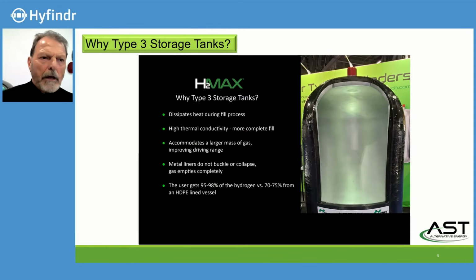Okay. And regarding the type 3, just also in comparison to the others in terms of operation and so on? Yeah, the type 3 has the big advantage. Aluminum is a very highly conductive material and therefore has a lot of dissipation of heat during the filling process. I'm going to show you a little bit of what happens during filling in another slide. So the high thermal conductivity really sucks in the heat during the filling process. And therefore we get more gas in the tank, and getting more gas in the tank means a larger range for the truck or wherever it's mounted.